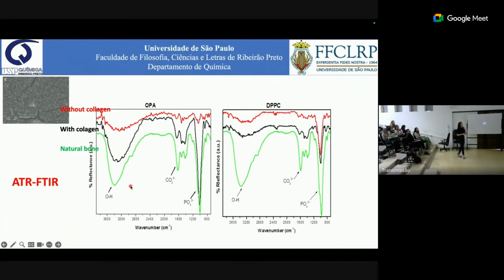We compared the composition of the coatings with the composition of a natural, fresh bone, and we see that this kind of coating composed by the needle-like particles were very similar by FTIR analysis to the bands we find in the natural bone. Moreover, the films containing collagen were much more similar to the natural bone than the films obtained in the absence of collagen.